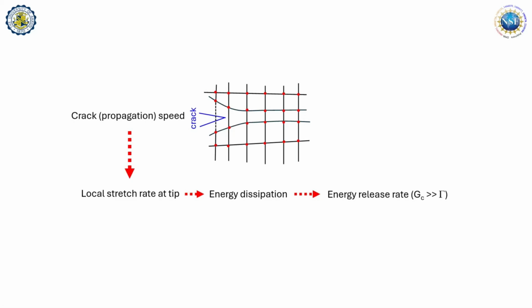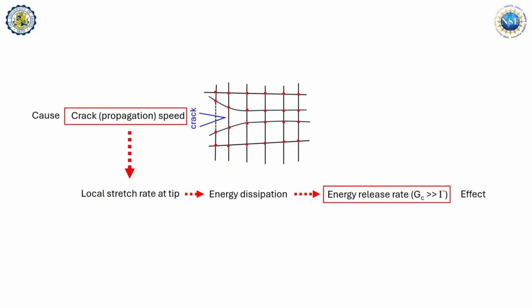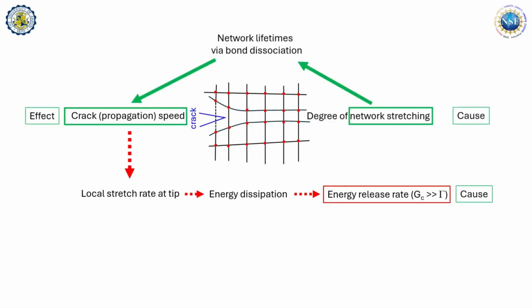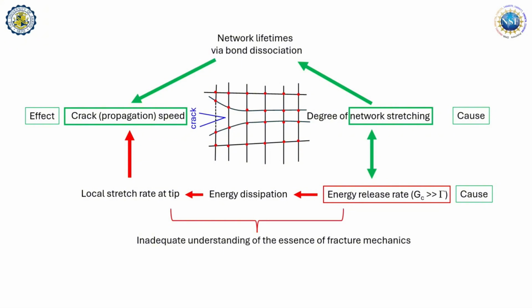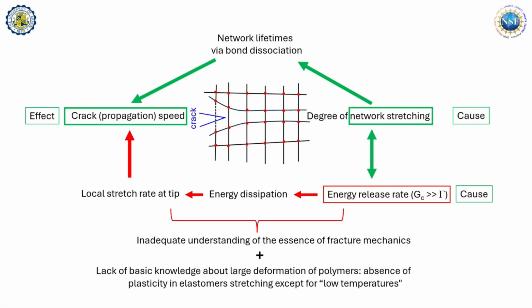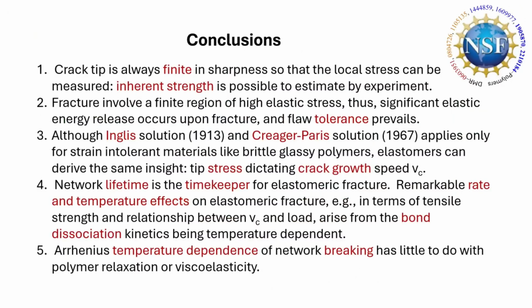So it turns out this is one way of thinking classically. The cause is the speed, the effect is the energy release rate, but the way we think about it is the reverse: what drives the speed is the lifetime of the bond. What drives the lifetime is how much you stretch, which you can calculate as a function, as the so-called energy release rate. So we got this cause and effect flipped. This is just a story where a deeper understanding of both fracture mechanics and solid and polymer physics is necessary to reach the right conclusion. So that's the conclusion. Thank you very much.